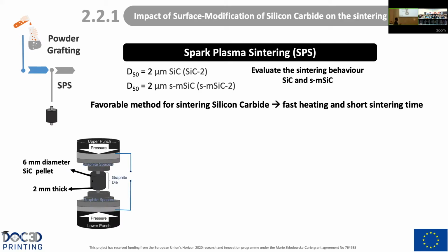So this is the setup of the sintering. This is a sintering technique which uses pressure driving powder compaction, in which a pulsed direct electric current passes through the sample. And here, with the powder, what we are going to manufacture are silicon carbide pellets with 6 mm diameter and 2 mm thickness.